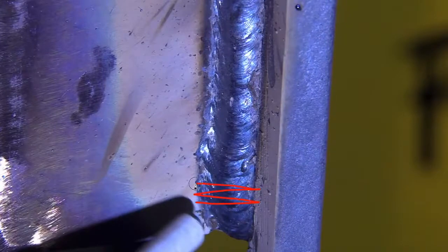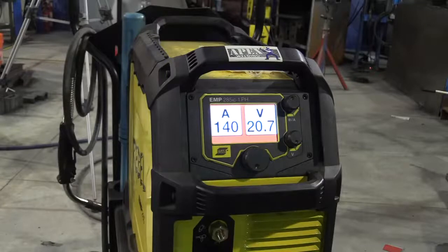The weave pass is just basically what's called a Z-weave. Goes just about like this. Not spending much time across the middle, pausing briefly on the toes of the weld to fill in any undercut. That's the way of it. 140 amps still. Hadn't changed the amperage a bit. In fact, the amperage will just stay at 140 for this Z-weave pass here, as well as the stringers.